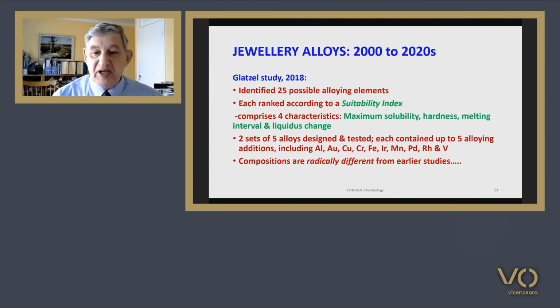They identified 25 possible alloying elements, and they ranked each element according to a suitability index. This comprised 4 characteristics: the maximum solubility in platinum, its hardness, the melting interval, and the liquidus change. They examined 2 sets of 5 alloys and tested them, and each contained up to 5 alloying additions. And these included elements such as aluminium, gold, copper, chromium, iron, iridium, manganese, palladium, rhodium, and vanadium.